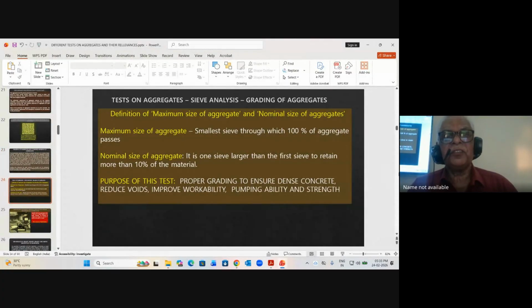So we have to understand the maximum size of aggregate and nominal size of aggregate. Maximum size of aggregate is the smallest sieve through which 100% of aggregate passes. Nominal size of aggregate is one sieve larger than the first sieve to retain more than 10% of the material. This nominal size is what we consider in the design mix, because we are allowing about 5 to 10% higher size aggregate also. That is very, very important.